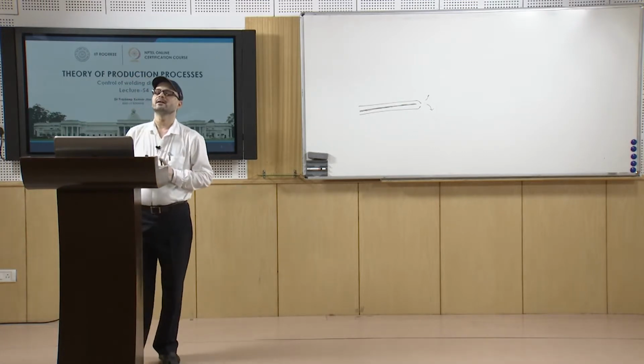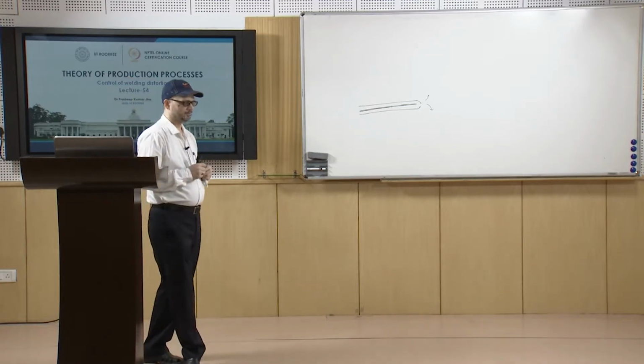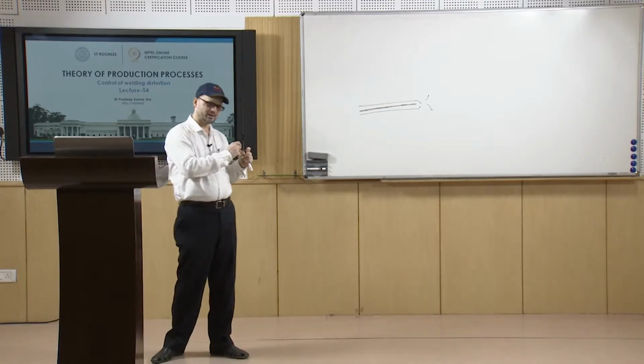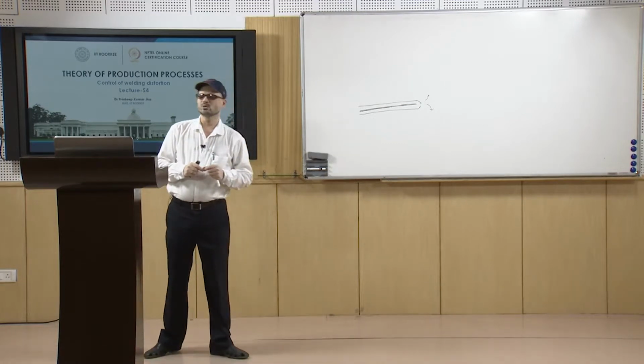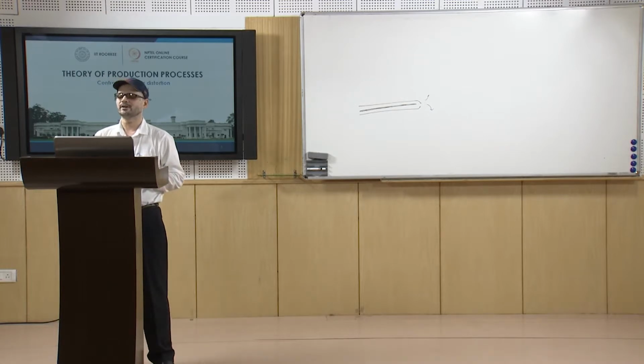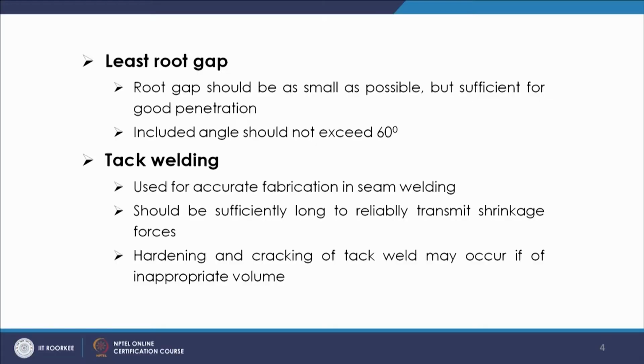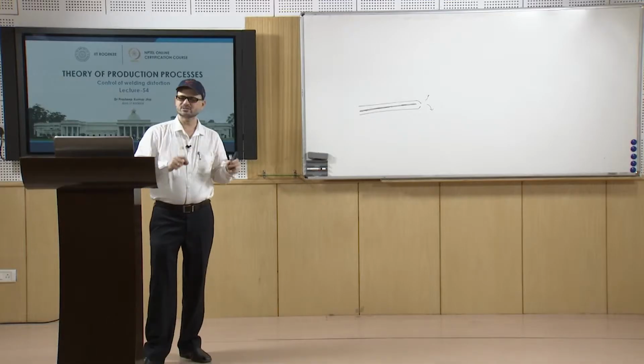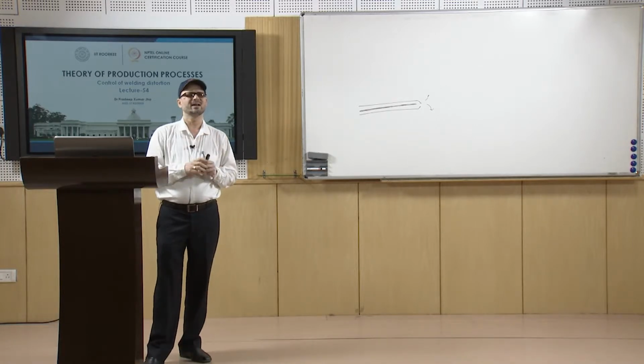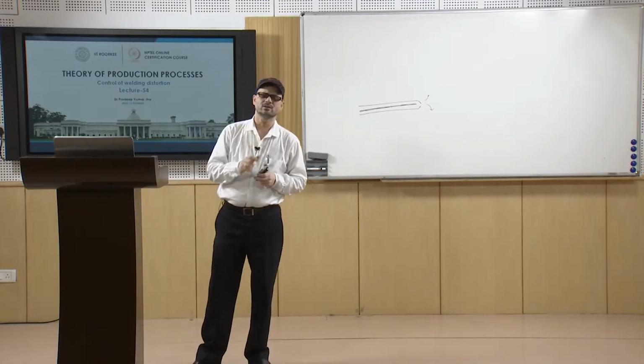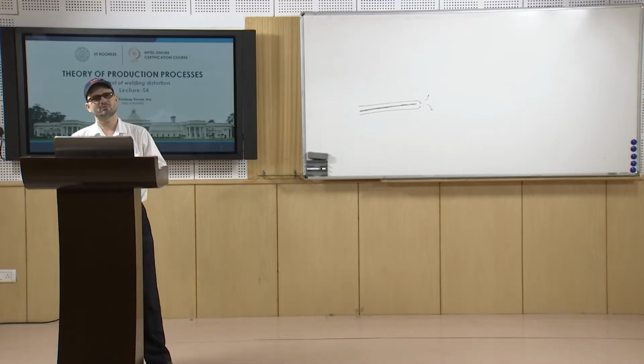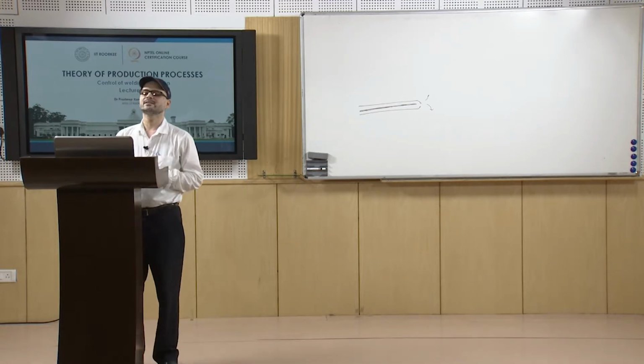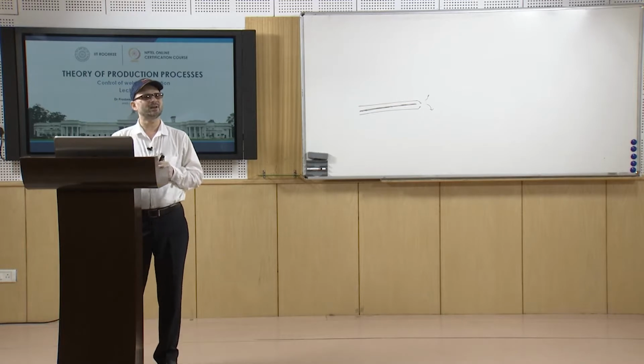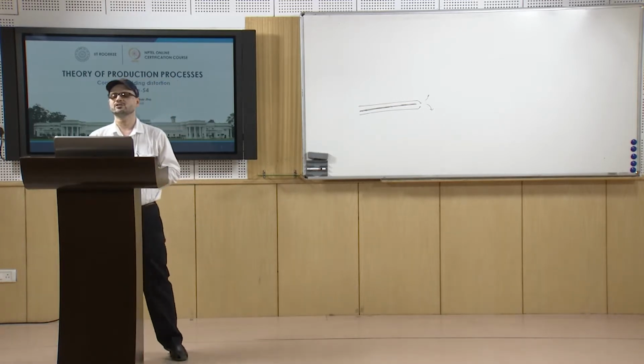Then second is the tack welding. So, tack welding is used normally for the accurate fabrication in case of seam welding. When you are welding along a seam and for larger lengths, then in those cases normally you use this tack welding, and it should be sufficiently long to reliably transmit the shrinkage forces. So, when you are putting the tacks, you must have the tack of certain length, and normally this length is a function of the thickness of the sheet which you are welding, or thickness of the plate, and this tack weld length is normally kept as about 2 to 3 times the thickness of the plate, so that it can reliably transmit these shrinkage forces.